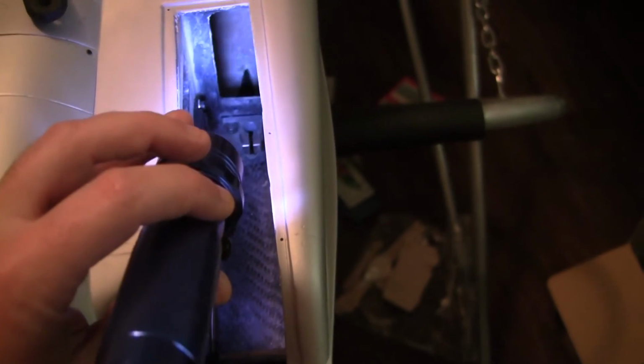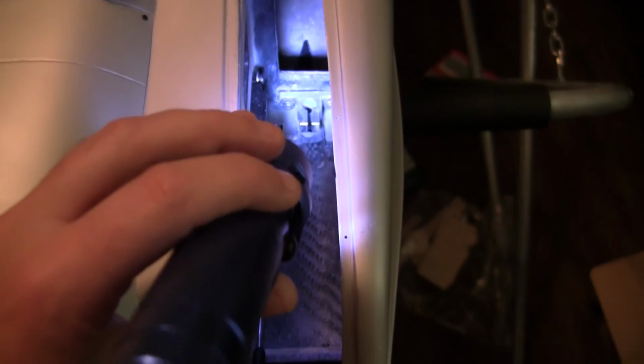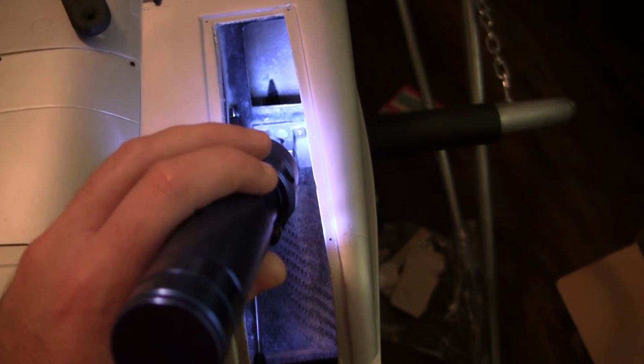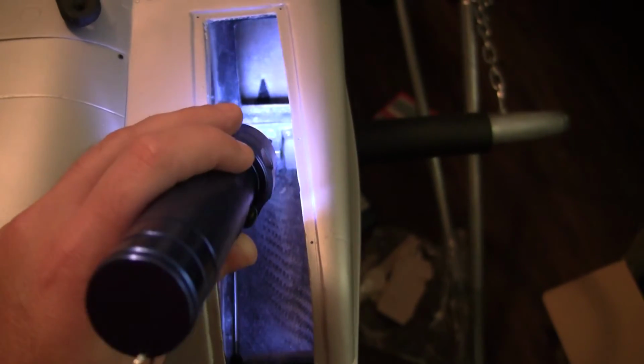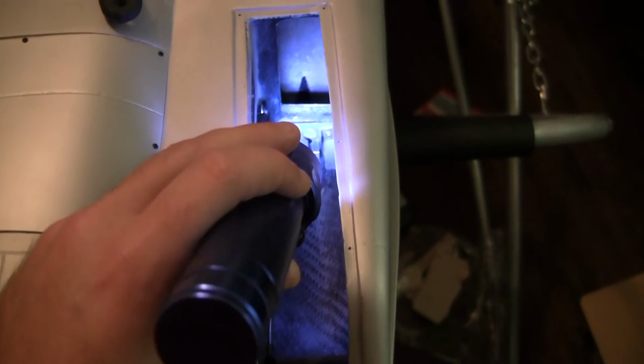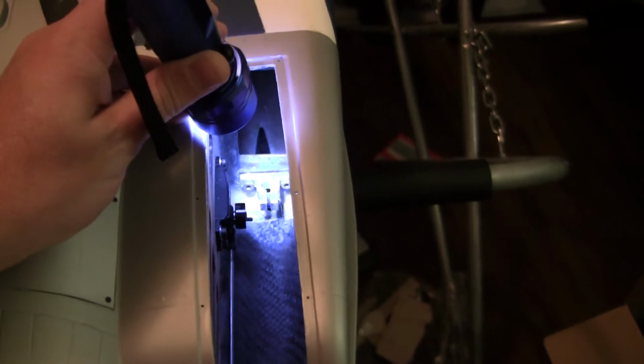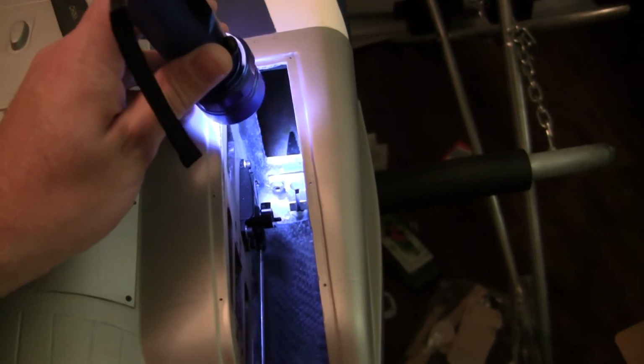I don't know what they used to laminate these honeycomb, but it's black like carbon fiber, but it's so thin that you can literally crush it with your hand. So over time, even if you have these installed and they're tight, we all know that with vibration, any kind of flexing and movement just crushes the honeycomb, especially when it has nothing to support it. If they had a ply on the same side as the bracket, that would fix the majority of it, but still it's a crushing force with that bracket and those bolts, so that's not the proper way to do that.